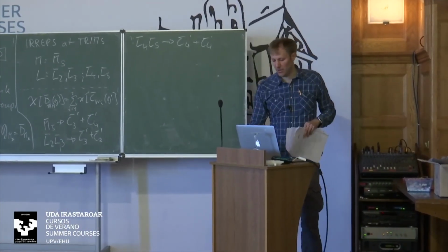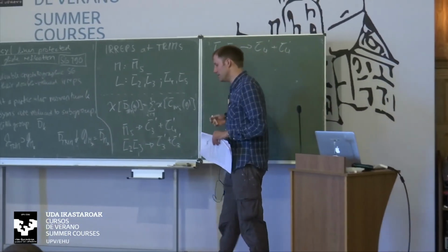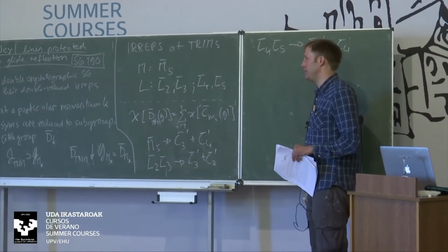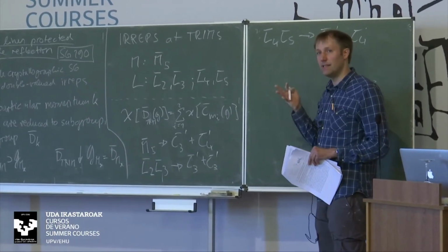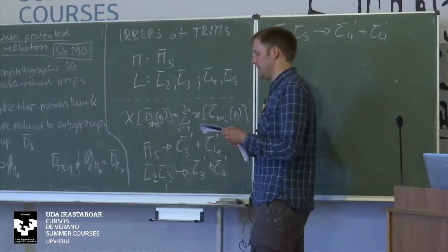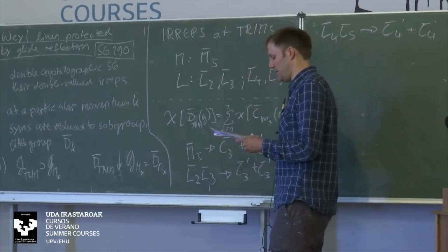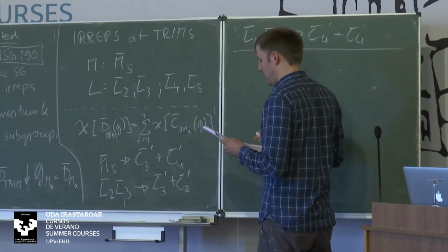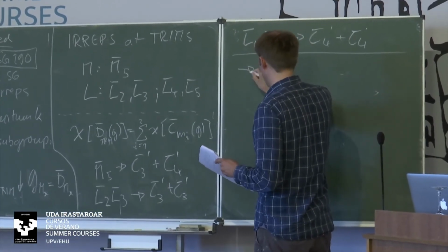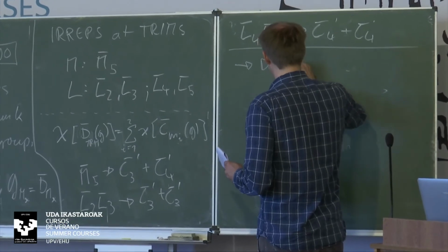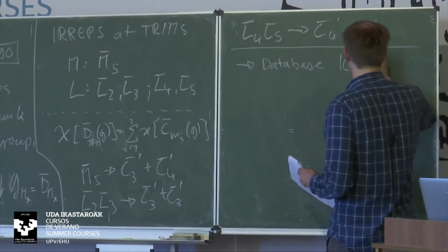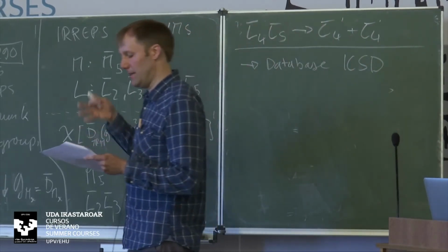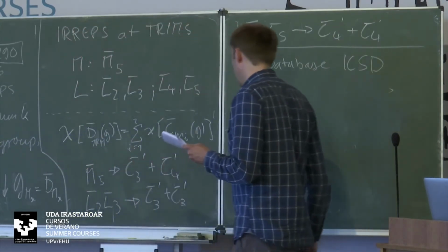Okay, yeah. So, to summarize, we have found in the space group 190 these nodal lines, and these occur for all the bands and for all materials in the space group. So I can now use this strategy to find a new material. What I have done already is you can look at these databases, for example this ICSD from Karlsruhe, and you plug in the space group 190, and then you get a list of materials which crystallize in the space group.